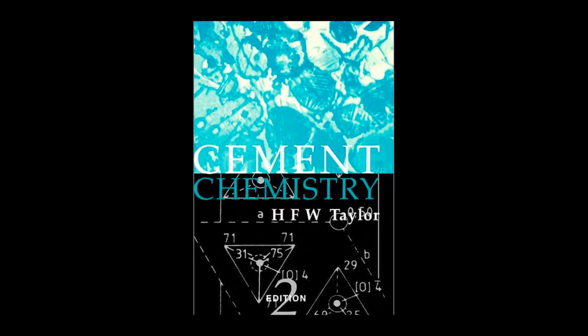Those impurities are essential elements like MgO, Al2O3, and Fe2O3 that substitute into the C3S lattice during clinkering. So they slot right into the crystal structure. They do. They change the crystal geometry just enough to make the structure stable at lower temperatures, locking in that reactive phase. For example, the amount of MgO that can dissolve into C3S depends heavily on temperature. You can get about 2% in at 1550 degrees Celsius, and that drops a bit at lower burning temperatures.